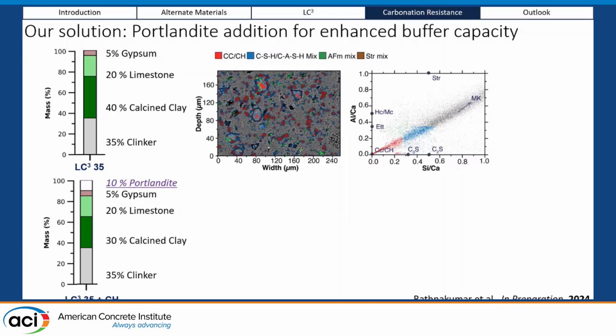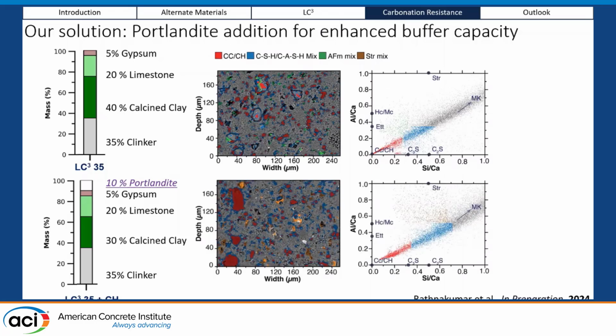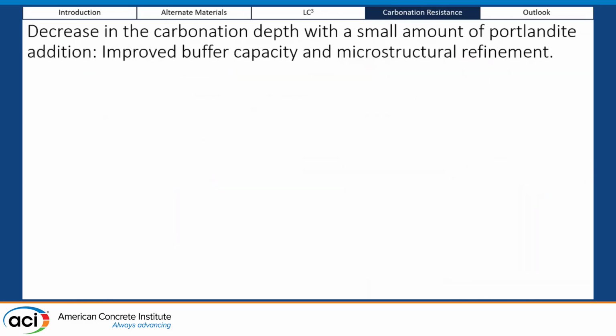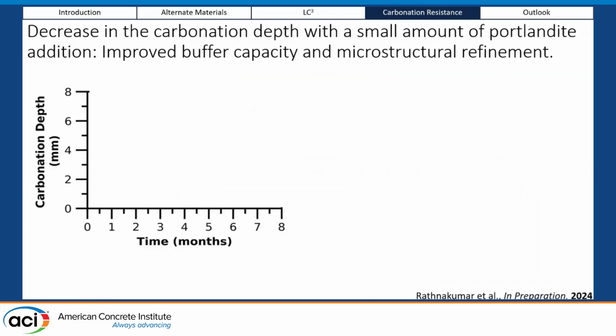What we see here are 2 SEM micrographs with their EDX maps. In the bottom image with the EDX data, we see a cluster of strätlingite, an AFm phase, depicted in this box. The reason we have strätlingite is the increased degree of reaction of the metakaolin with this added amount of portlandite, which causes a refinement of the porosity, and that also enhances its buffer capacity. With that in mind, we tended to reduce the amount of portlandite because portlandite also has a CO2 footprint.